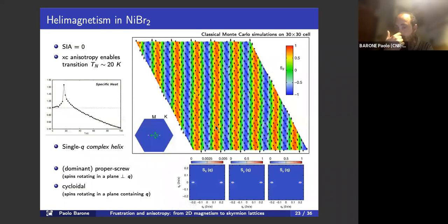To understand this, we performed classical Monte Carlo simulations, feeding in the model parameters extracted from ab initio. So we focus first on the nickel dibromide case. From our calculation, there is no single ion anisotropy, but the presence of the exchange anisotropy enables a transition, which we estimated to be around 20 Kelvin, to a spiral phase, which is called here a single Q phase, because I told you there are three possible solutions for the Q.